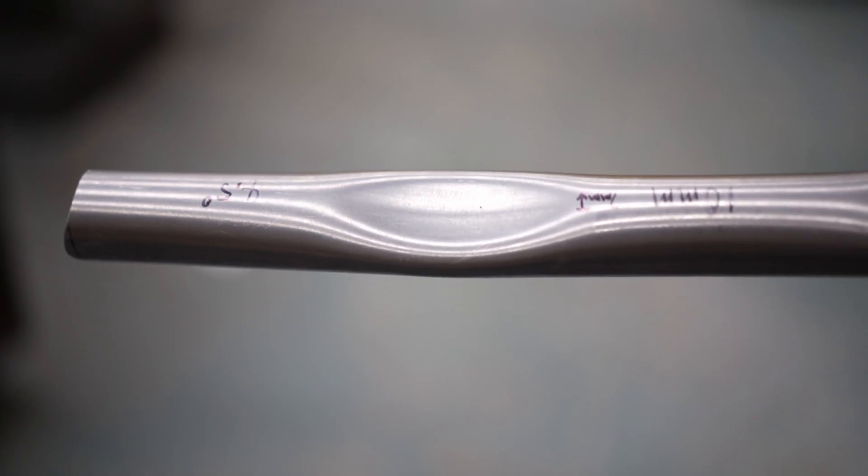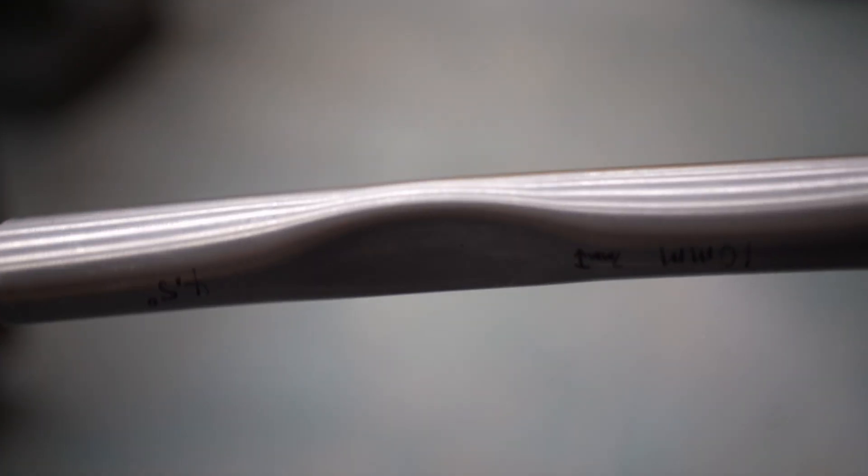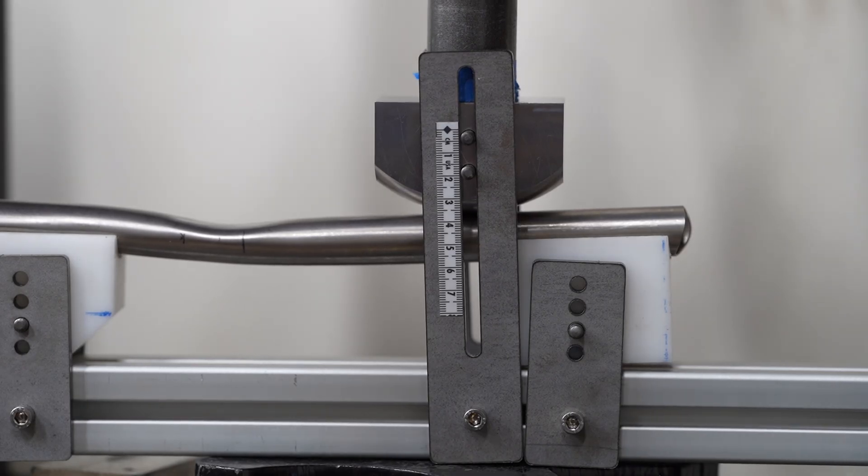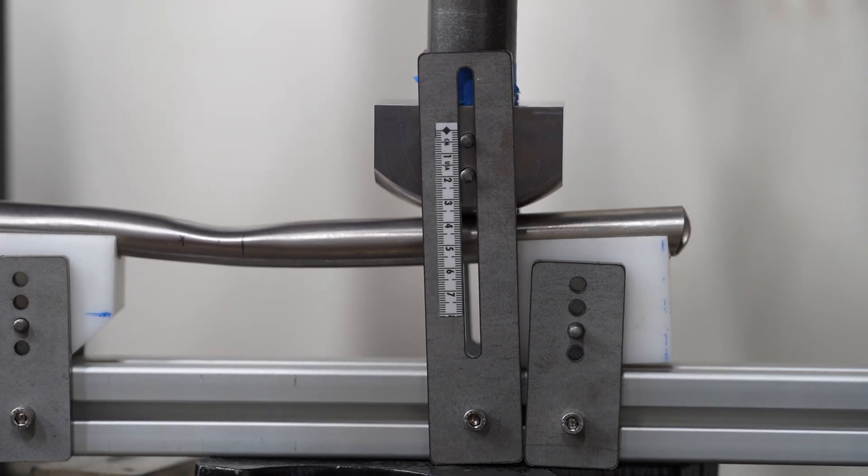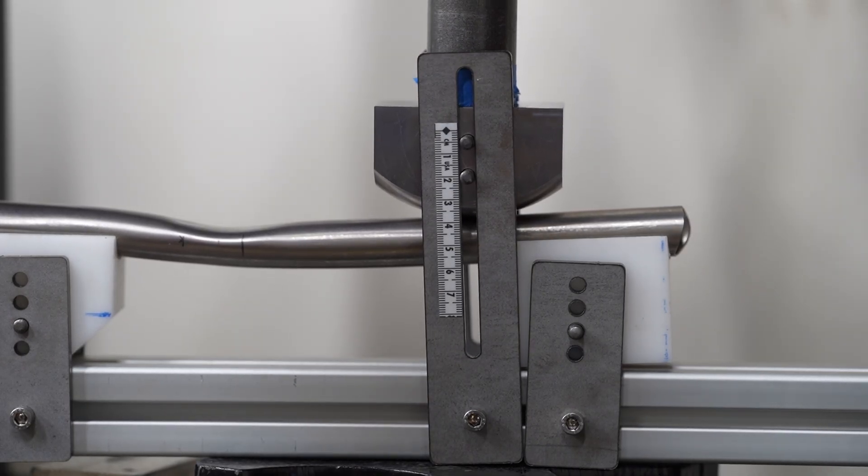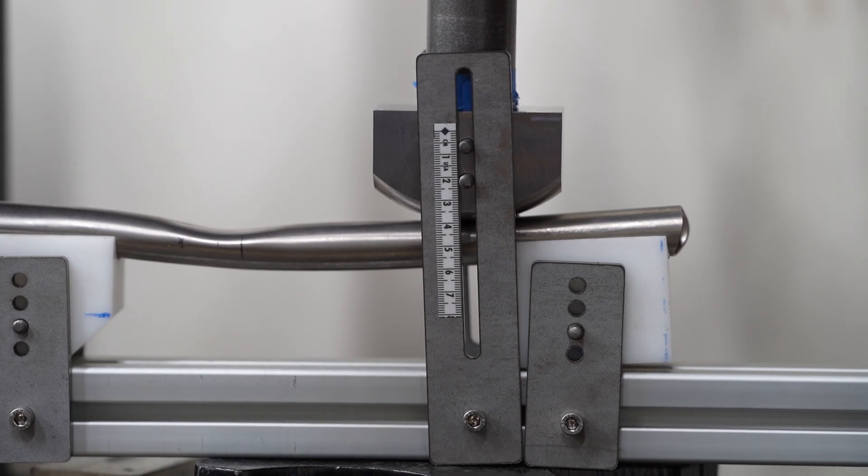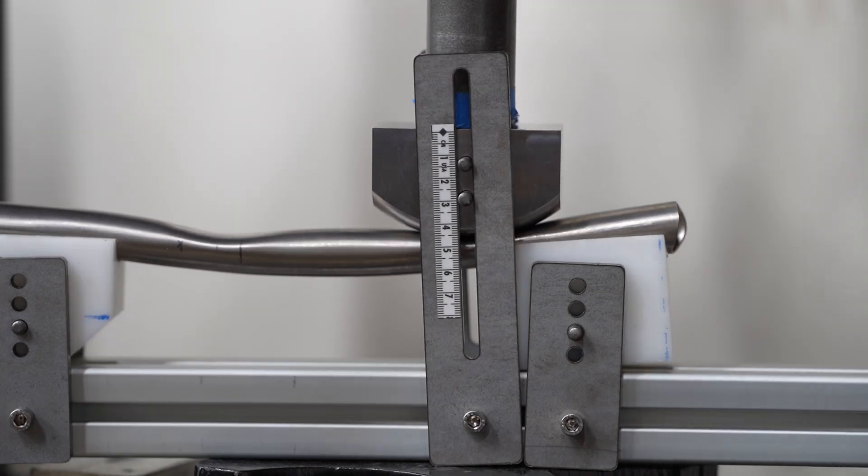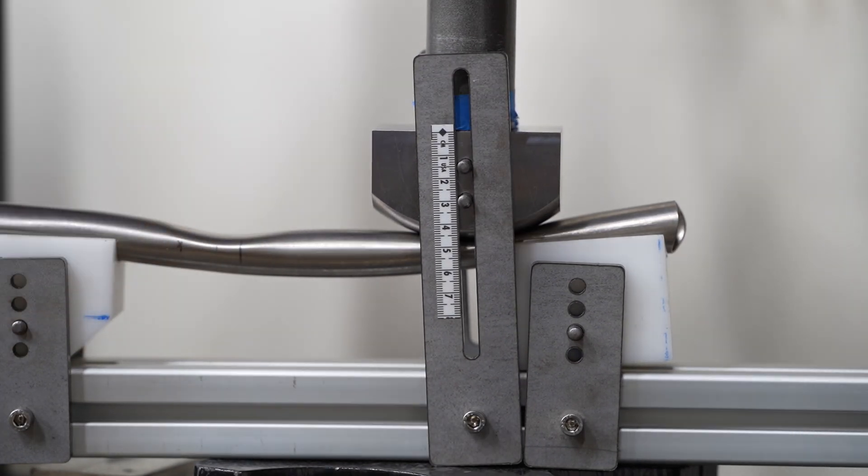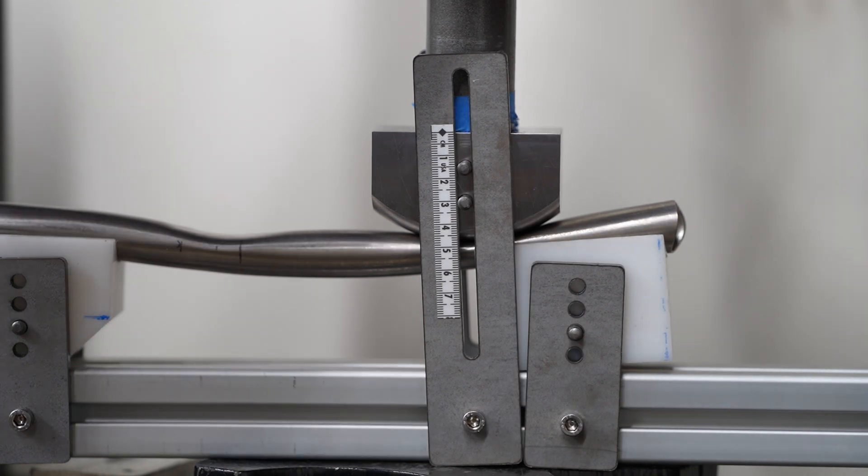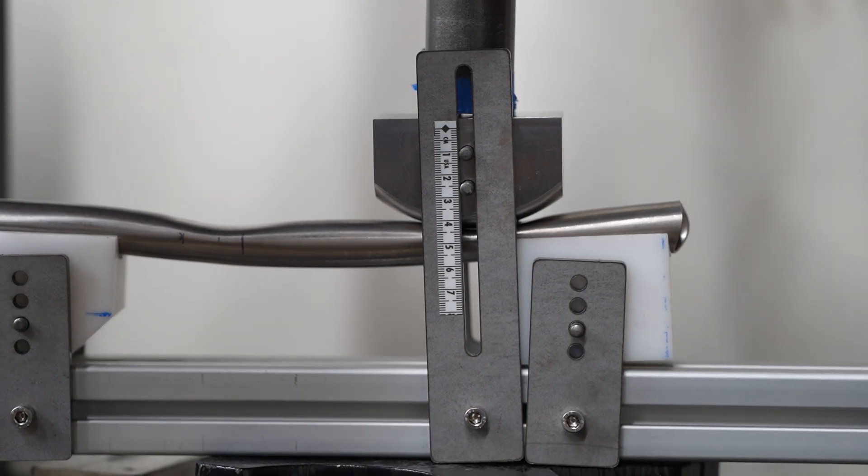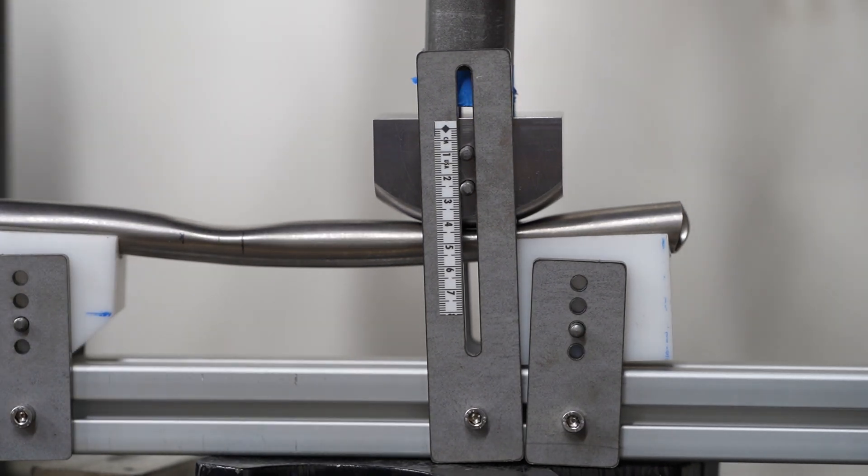I was honestly surprised how good the results were. The fixture works really well. The dimples come out very even and repeatedly, and the fixture works on bent chainstays. If you press the die 10mm deep into the tube, the resulting dimple is 6mm deep after the spring back, and the tube bends approximately 4 degrees.